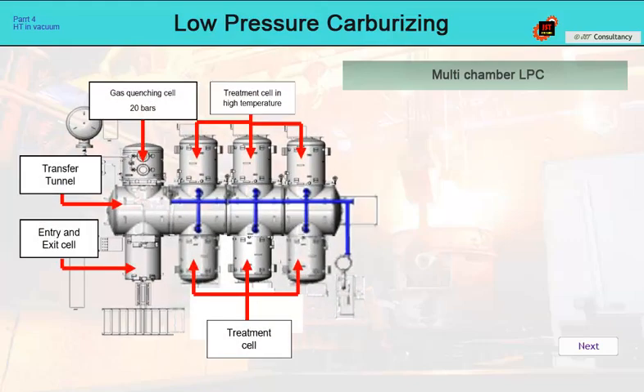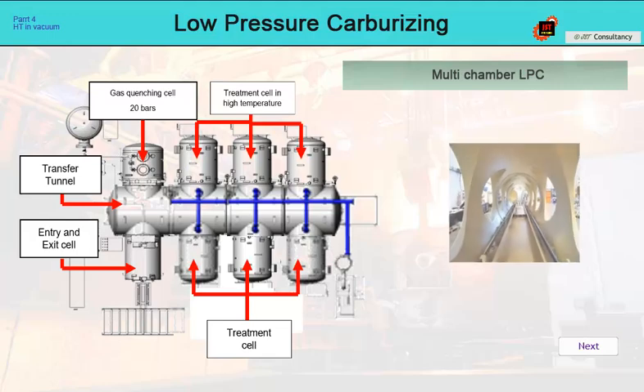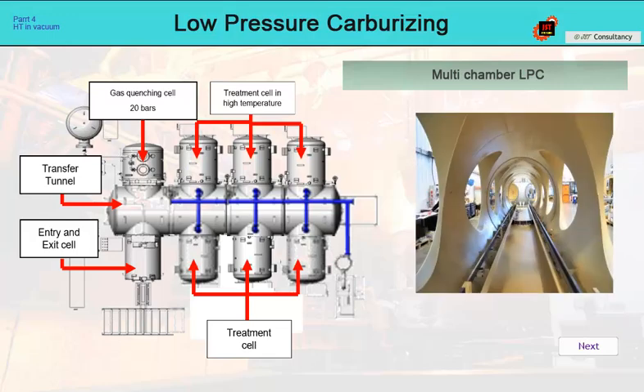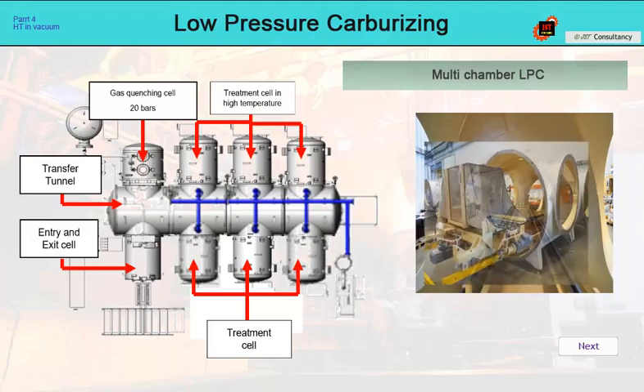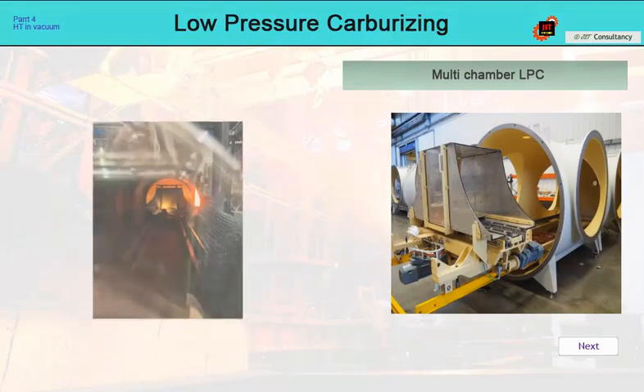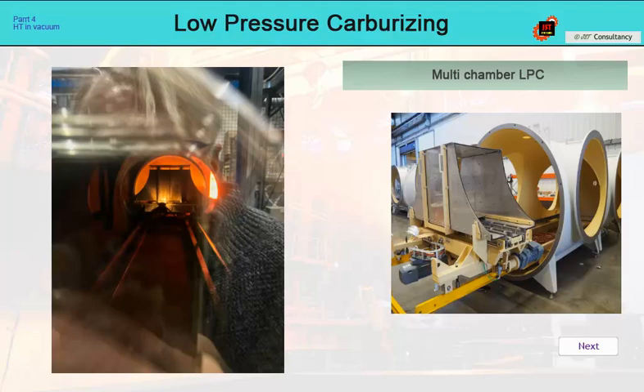The modular vacuum tunnel allows you to connect working chambers that can be of different purposes: for carburizing, for heating to high temperatures up to 1,250 degrees Celsius, for brazing, tempering, or nitriding, and nitro-carburizing. Inside the vacuum tunnel, there is a transport system that transports the batch between the individual chambers in a vacuum. Up to 14 of these cells can be installed in this way. However, it depends on the implemented technology, because we still have to keep in mind the time between the batch being removed from the carburizing chamber and being introduced into the quenching module.